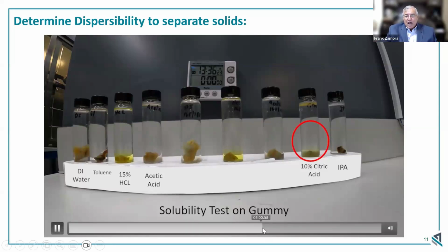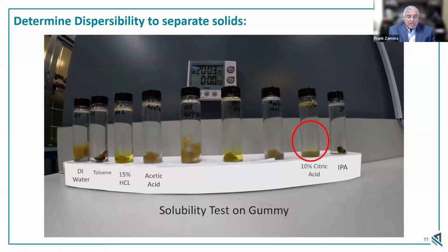So as we go through time, all we end up with is a better hydrated polymer. This DI with a little bit of surfactant did actually enable it to hydrate a little bit faster. Simply what's happening here is the surfactant is actually helping pull some of this oil, allowing the fluid to come onto the polymer and fully hydrate it.